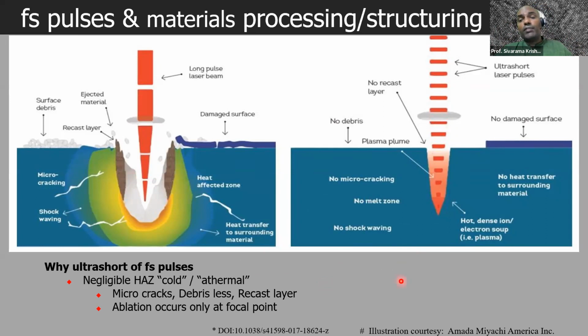And on the right hand side, we have femtosecond pulses. Owing to the way in which they interact with matter, they essentially achieve this knife through butter type of interaction, right? There is almost no cracking, hardly any melting. If you control the conditions well, there is almost no shock wave and minimal or no heat transfer. In fact, one could, in transparent materials, even do subsurface material modification without damaging the top surface at all.